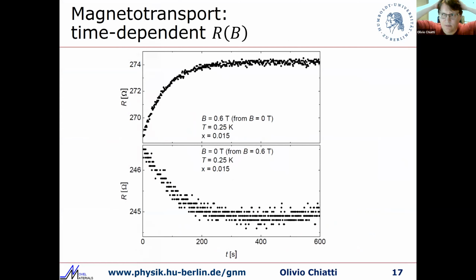We don't expect a hysteresis like we see with ferromagnetic materials. What we observed here, for example, is if you sweep the field and then stop sweeping the field and sit there for a while, the resistance changes with time until it stabilizes. And it doesn't seem to depend on the sweep rate, but it seems to depend on which direction we sweep the field. So we don't think it's ferromagnetic.